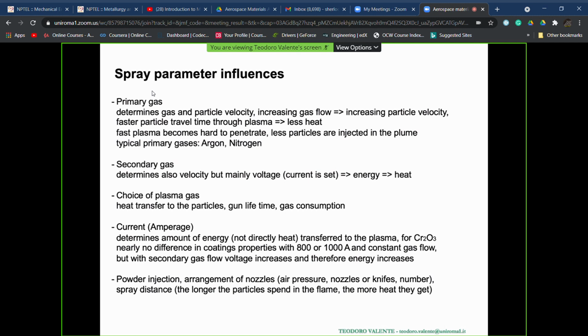going to be sprayed. Fast plasmas also become harder to be penetrated by the particles through the injection mechanisms. And if it happens, this means that fewer particles are injected in the hot area, that is the plume. The typical mixture of primary gases which are going to be used is argon and nitrogen.